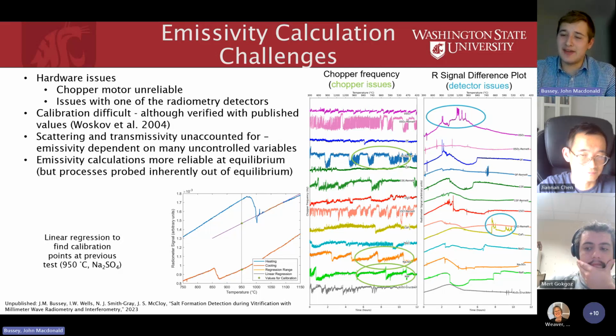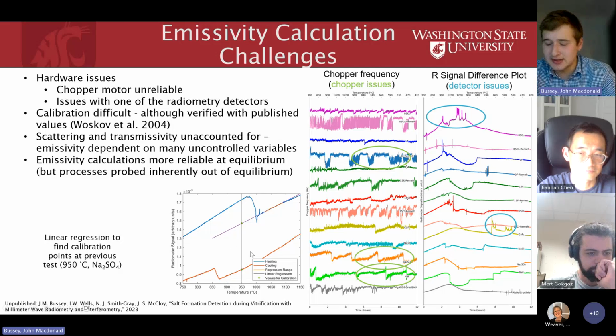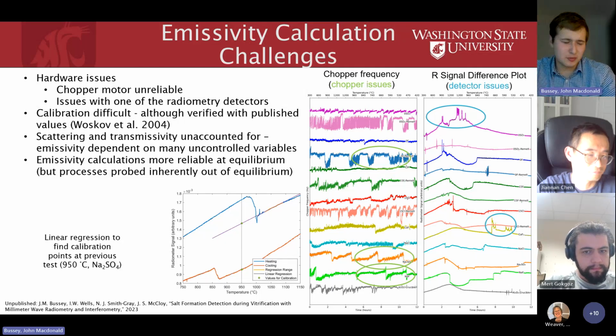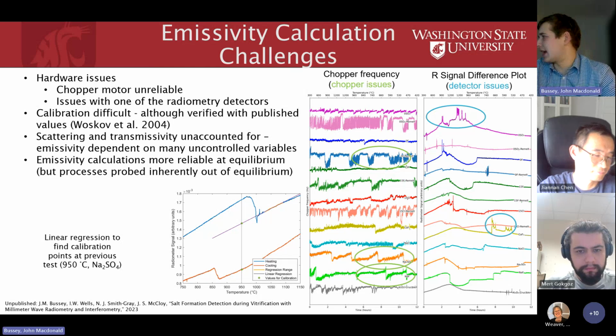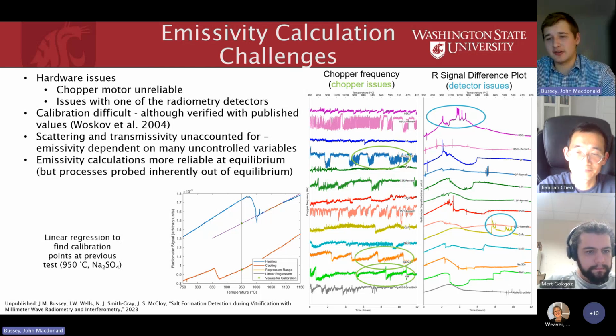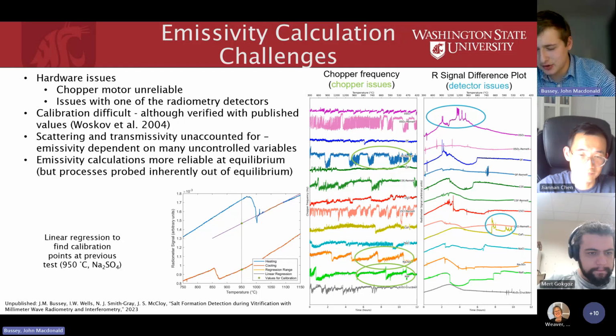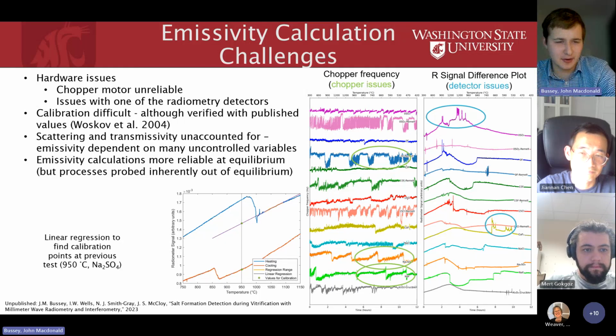Some of the main issues we had is we were having detector issues. You can see here on the right, some of these features that I have circled are indicative of issues with one of the detectors. Particularly, it really did not like getting cold, not much below 65 Celsius. And in the winter in Pullman, when it's regularly 0 degrees Fahrenheit outside, oftentimes facilities do not keep the buildings warm enough to keep our detectors happy. Another issue we have is the chopper. The motor on the chopper appears to be slowly dying. And since I'm currently in Sweden on an exchange program, I did not have time to recollect the data, but we see that's also introducing some artifacts.